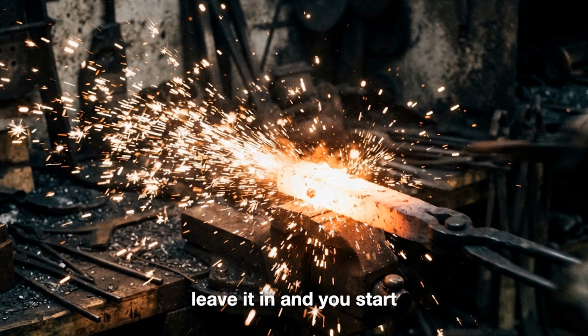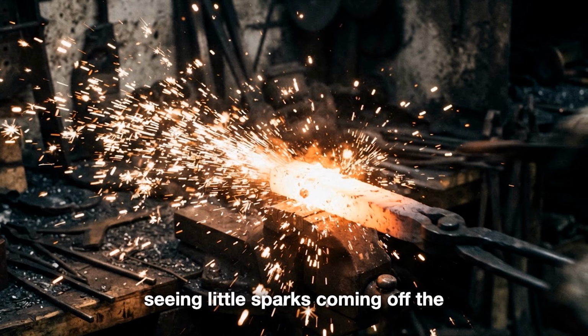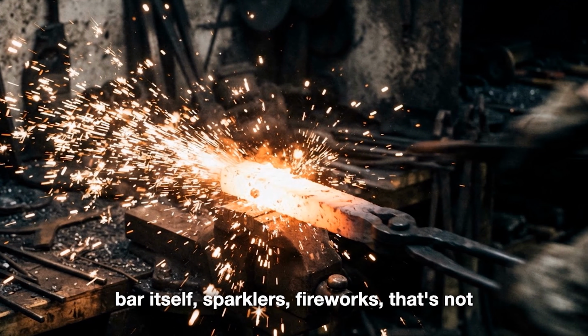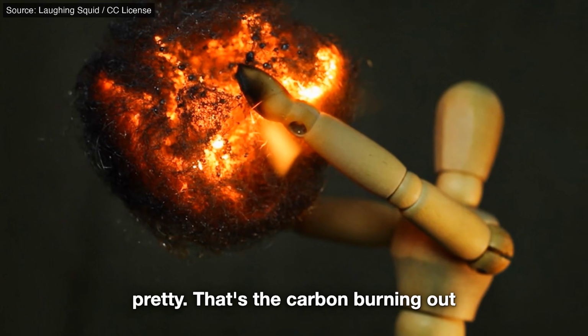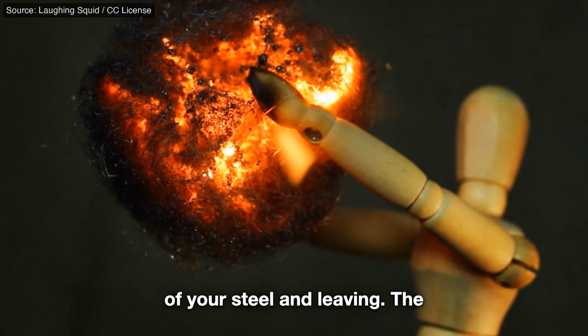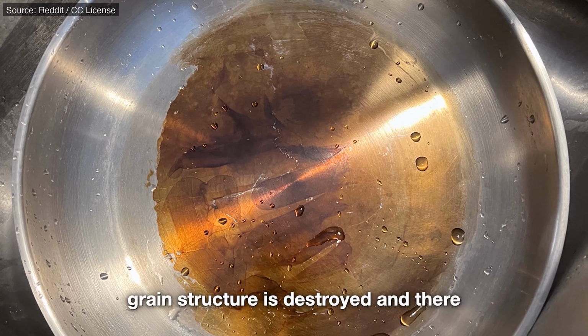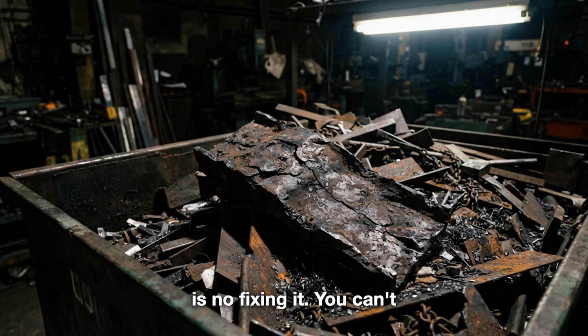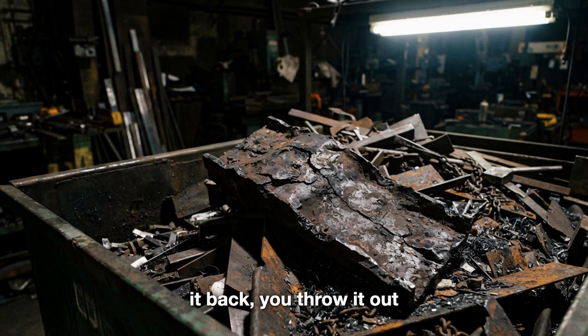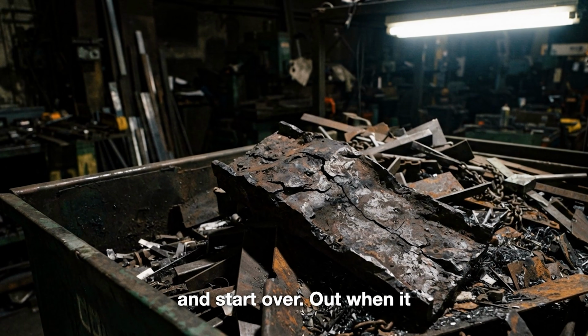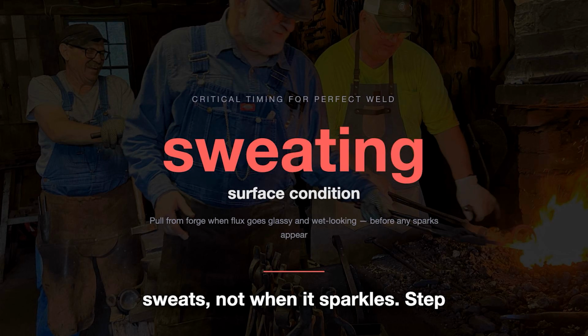If you leave it in and you start seeing little sparks coming off the bar itself, sparklers, fireworks, that's not pretty. That's the carbon burning out of your steel and leaving. The grain structure is destroyed and there is no fixing it. You can't heat it back. You can't hammer it back. You throw it out and start over. Out when it sweats, not when it sparkles.